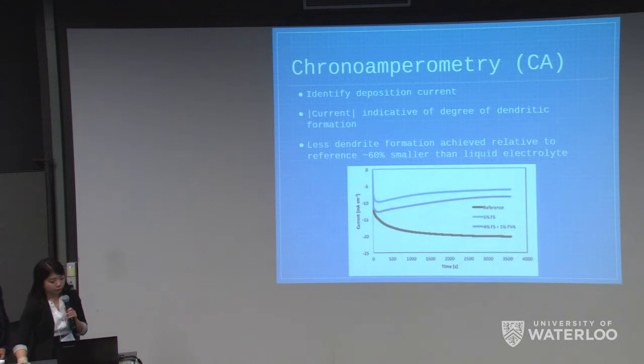The higher the absolute value of this current density after reaching equilibrium, the more likely that deposition of dendrites will occur. And the lower the absolute value would be the opposite, where we will have a more smooth surface. Literature shows that the absolute current density for a reference electrolyte currently in use is approximately 20 milliamps per centimeter squared. Thus, an absolute value lower than 20 milliamps per centimeter squared would have better dendritic formation. And with our design, it was approximately 60% smaller than the liquid electrolyte in dendritic formation. But as our results showed, our design electrolyte showed a significant decrease, but not as good as 5% silica.